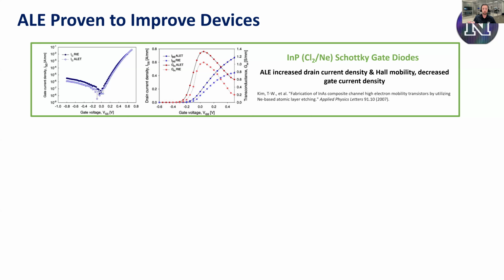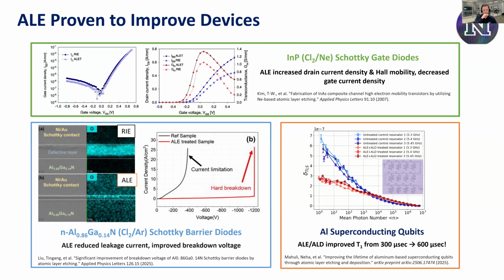And my favorite example, Neha Mahuli, she was a postdoc in Steve George's group, which, if any of you are in the ALD space, you know is a really important research group. They've done incredible stuff for a long time. Well, she's at Amazon now in the quantum team, and they were able to show that using an atomic layer etch, atomic layer deposition process in which they took the native oxide that's formed after their typical etch of an aluminum device, removed that damaged native oxidized layer with atomic layer etch, and then in situ grew back a higher quality ALD oxide, they were able to double the coherence time of superconducting qubits. So there's clearly something here. Clearly, atomic layer etch has a place in quantum device fabrication, as well as the fabrication of all sorts of other devices.